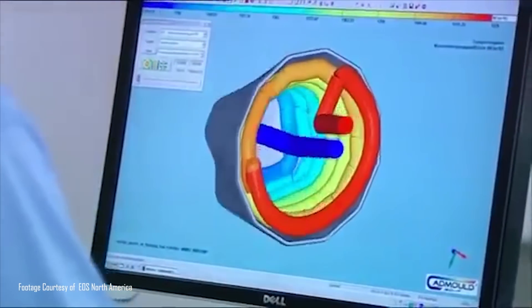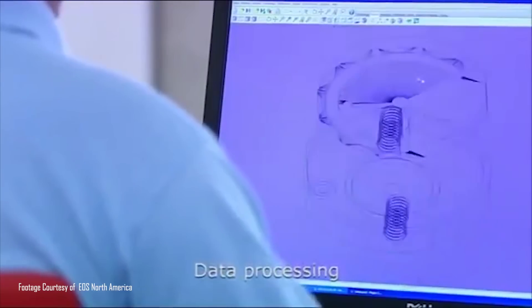Of course, you're talking about injection molding. For those of us who are older industry veterans, we remember that you may have mold inserts, but the mold base itself was cross-drilled typically, and then the water cooling lines were manifolded — it's a source of leaks and tremendous difficulties. But conformal cooling gives you another advantage: it lets us run the water lines near net shape to the part and the actual surface for the molding or die casting component. That allows us to better control the temperature during the molding process — you can do both heating or cooling depending on the application. The general benefits are reduced cycle time, so time per shot goes down, and because the temperature on the tool surface during molding is more uniform, you're going to get better plastic qualities in your finished end-use part.